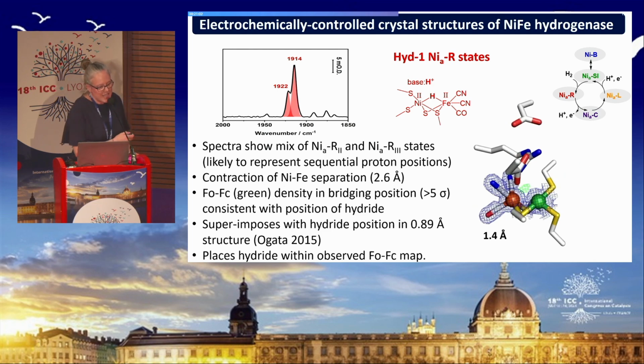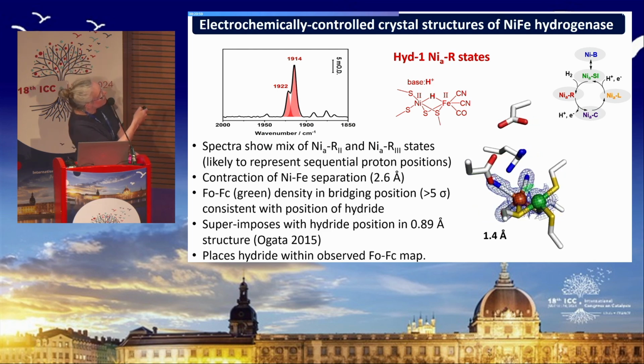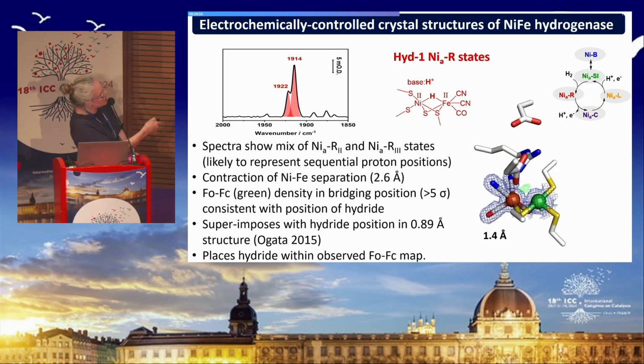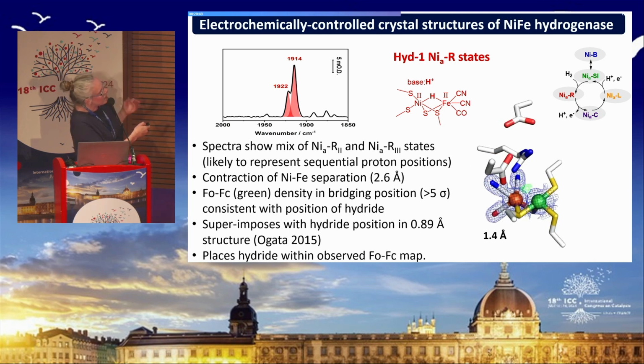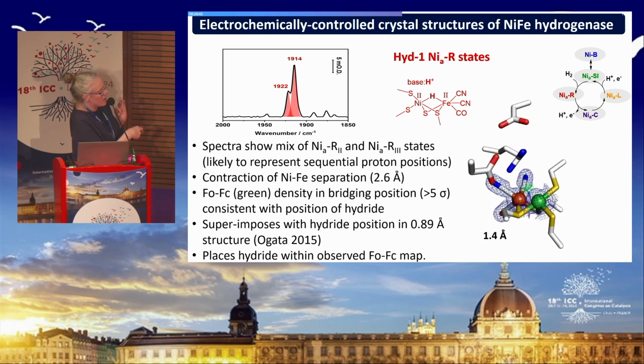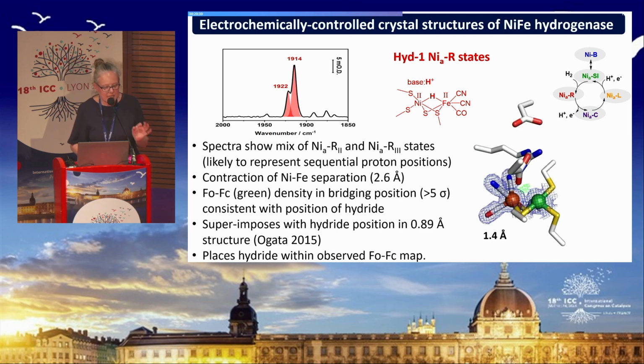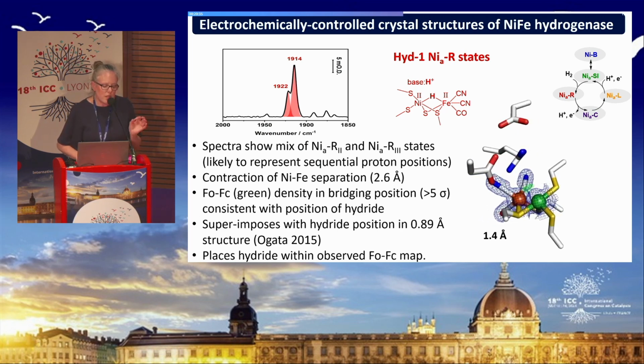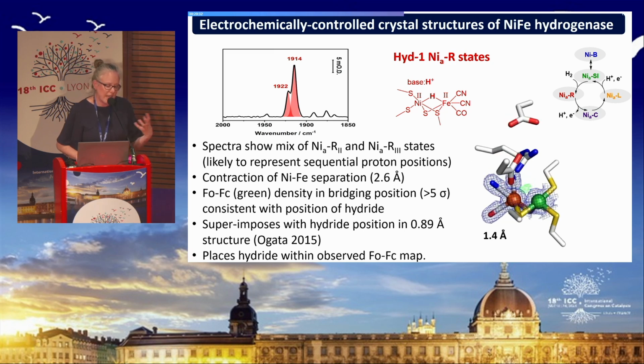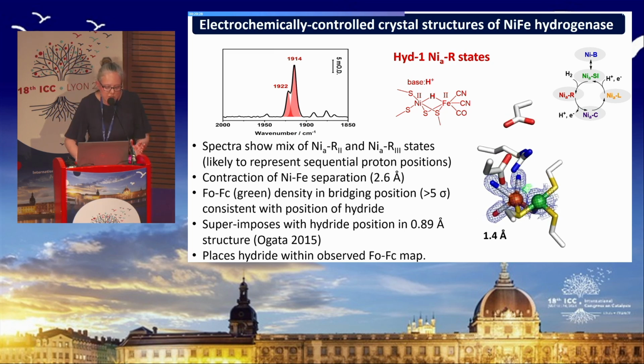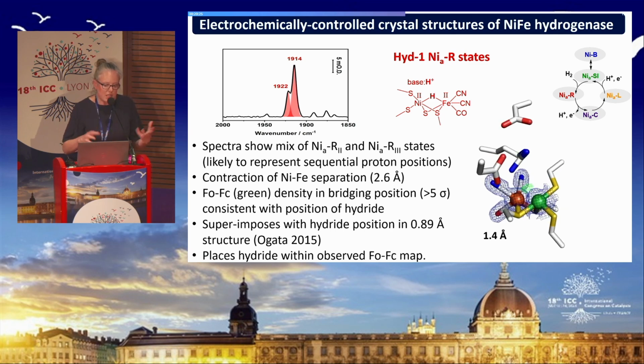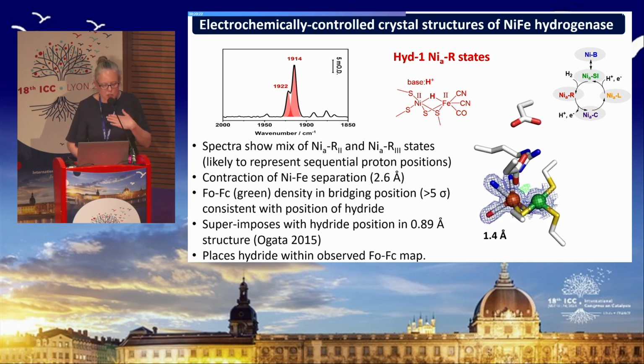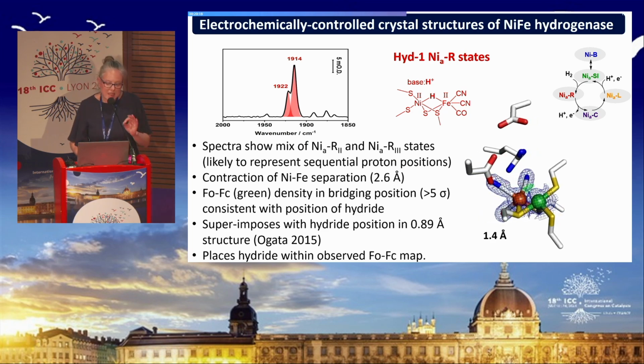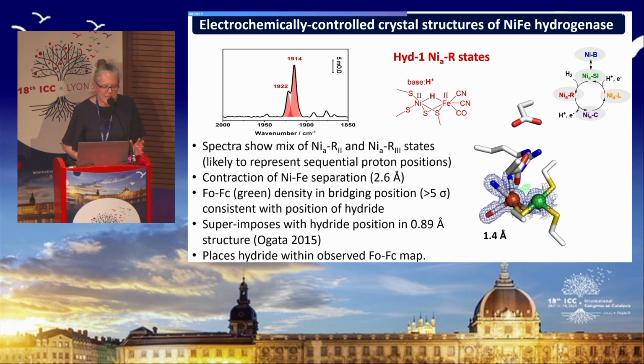We then move on to the reduced nickel R states. Now in the CO region, we do have a mixture of 2 states, and we think these are these 2 protonation substates that we label nickel R2 and nickel R3. And when we record the structure of this, we see electron density now between the metals, which would be consistent with a hydride that we expect in the nickel R states. And this superimposes beautifully with the hydride position in a super high resolution structure of nickel R, reported by Ogata's group in 2015, where that was likely a mixture of all the different nickel R states. So that places the hydride within the metals, the bridging position as expected.